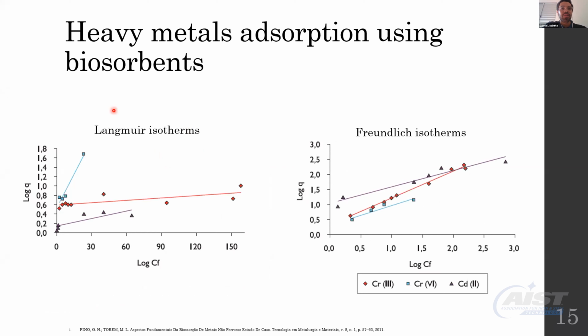The Langmuir isotherm and the Freundlich isotherm were constructed to evaluate the best fit for all the adsorptions. The bivalent cadmium and hexavalent chromium were best fitted by the Langmuir isotherm, while the trivalent chromium was best fitted by the Freundlich isotherm. It was found that all adsorptions were favorable, showing that the coconut fiber is a good adsorbent.